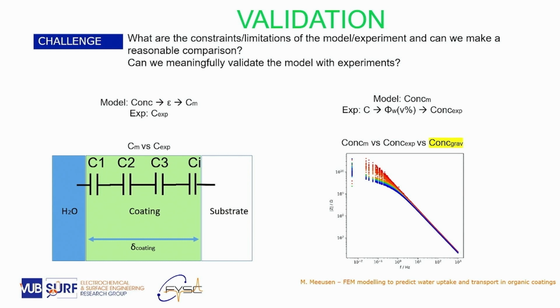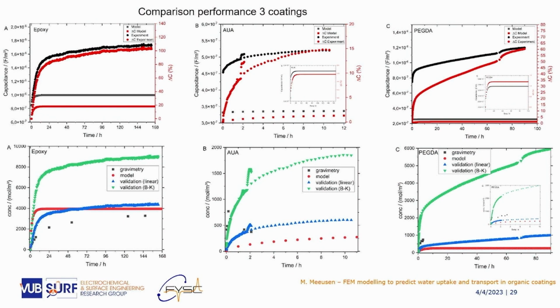So this has nothing to do with electrical equivalent networks anymore. You start with a physical description of your coating. You calculate the electrolyte uptake, and out of that you calculate the virtual capacitors. And with that, you try to compare the real capacitor to the calculated one. So these are the type of comparison data we have at the moment, and we still have problems. Because you see, the model is predicting sometimes a completely different relation, sometimes it is better, between the real measurements and the calculated or predicted values.